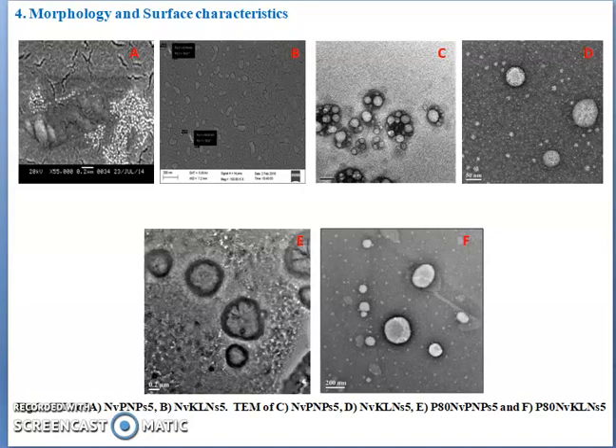negative in charge. Morphology, surface characteristics: all the uncoated nanoparticles, this is polymeric, lipid, are having a very small size, below 100. TEM images show that they are very small in size, 50 nanometer. After coating, their size increases. This is for polymeric, polysorbate 80 coated. The coating layer can be easily seen. This is for lipid. The coating layer can be seen. It actually increases the size to 200 nanometer.